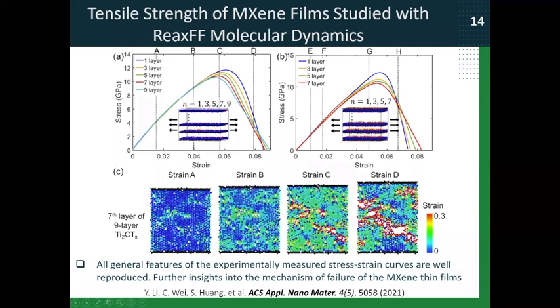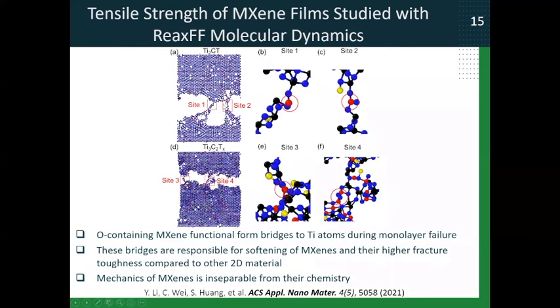And then finally, when we looked closer at the edges of the forming cracks, we found another interesting effect. And that brings us back to the very first slide about MXenes, when I said it's important to remember that the surface is coated with functional groups. And here we observe this effect of functional groups on mechanical properties. So what happens is this: when you stretch MXene and it starts to break and you form the crack, then oxygen-containing groups, which are attached to titanium atoms, oxygen is two-valent element. It prefers to form two bonds, right? When you start to separate titanium atoms